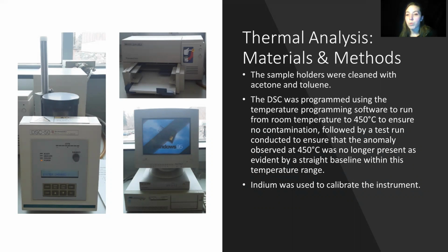The test run went from room temperature to 450 degrees Celsius. However, an anomaly was observed at 450 degrees Celsius, so another test run was completed to ensure that the anomaly was no longer present. Indium was then used to calibrate the DSC-50.